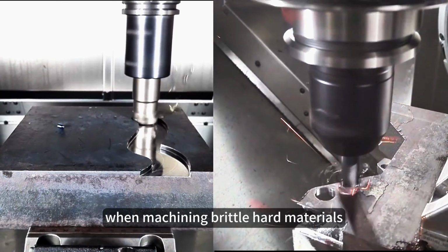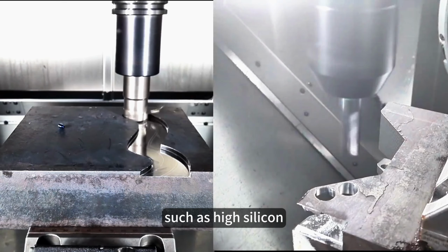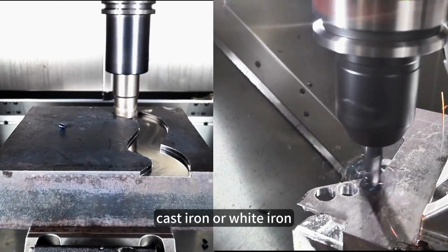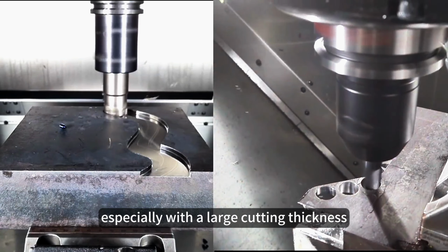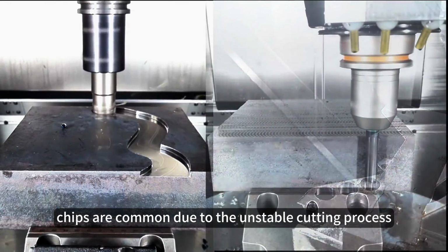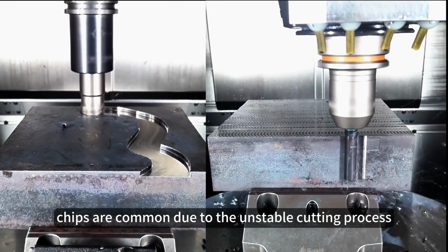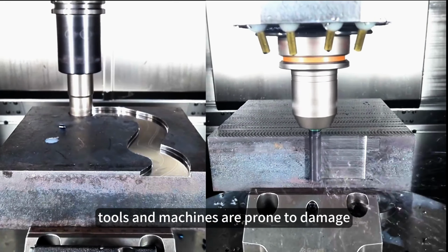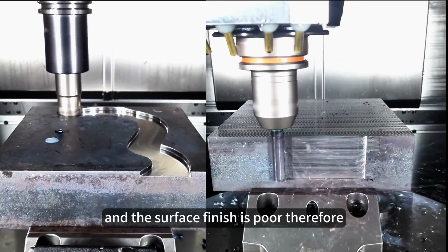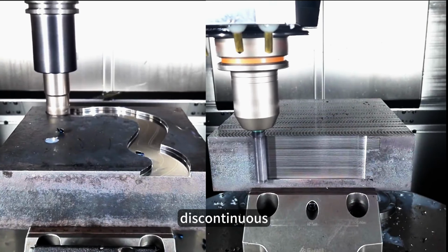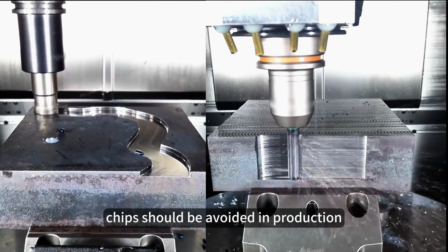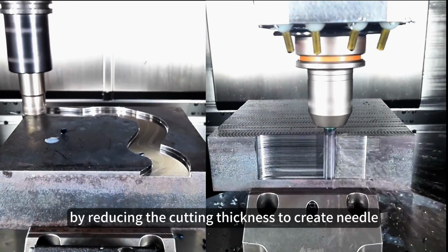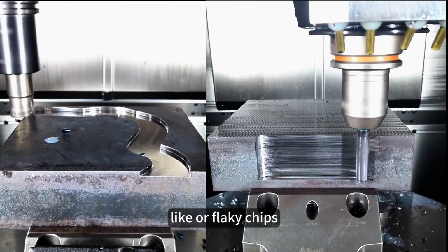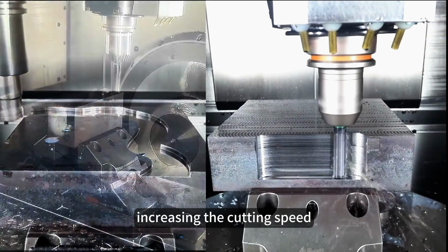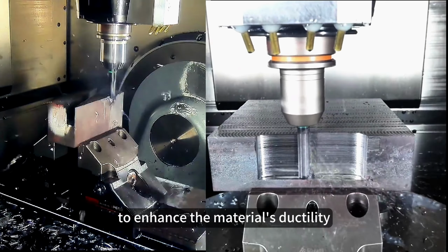When machining brittle, hard materials such as high silicon cast iron or white iron, especially with a large cutting thickness, discontinuous chips are common. Due to the unstable cutting process, tools and machines are prone to damage, and the surface finish is poor. Therefore, discontinuous chips should be avoided in production by reducing the cutting thickness to create needle-like or flaky chips and appropriately increasing the cutting speed to enhance the material's ductility.